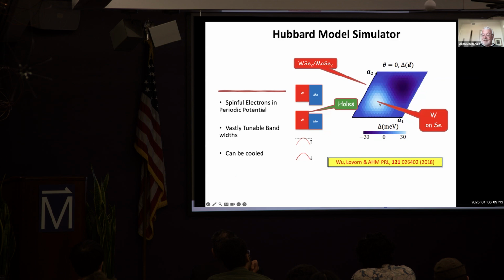If I look at low energy states, there will be favored energetic positions in each unit cell of the moiré pattern, and the holes will tend to go to those positions. And in order to tunnel from one of those favored positions in one moiré cell to another, the electrons have to go through classically forbidden positions, and that means that the widths of the bands of the effective periodic moiré Hamiltonian can easily be adjusted to very small values by making the moiré period long, so that you have to tunnel for a long distance through classically forbidden region. So in the end, this system is a realization of a Hubbard model. It's basically as close to a real Hubbard model as any physical system.